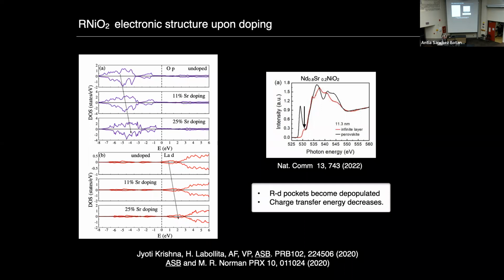Now, just to tell you a few words about doping, remember that when we dope is when superconductivity arises, so it's important to look at what the electronic structure looks like there. What we find is that it becomes more cuprate-like. How does that translate into this? Well, the rare earth D pockets become depopulated. You can see how they shift to higher and higher energies as you dope. So they move farther away from the Fermi energy. There is this vertical line here again. In addition to that, the charge transfer energy decreases with doping. What you see here is how the oxygen P states also move to higher energies, while the nickel D states, which are somewhere around here, are actually not moving. I didn't plot them here, but you can take my word on that.